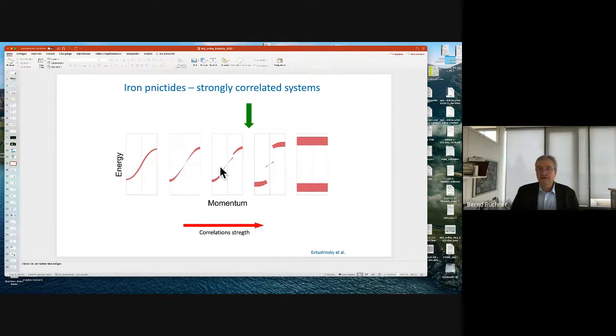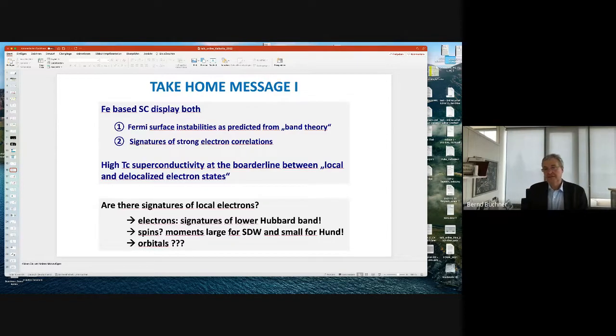So we have clear features also of correlations. And this is, let's say, my first very short take-home message. These iron-based superconductors display both. They display these Fermi surface instabilities as predicted from band theory, so these nesting instabilities, but they also clearly show the signatures of strong electron correlations. So in some sense, this superconductivity occurs at this borderline between local and delocalized electron states.